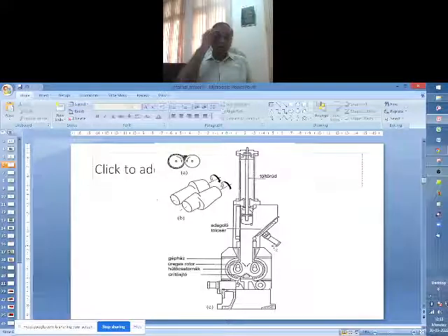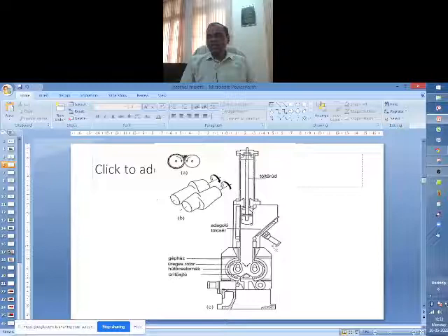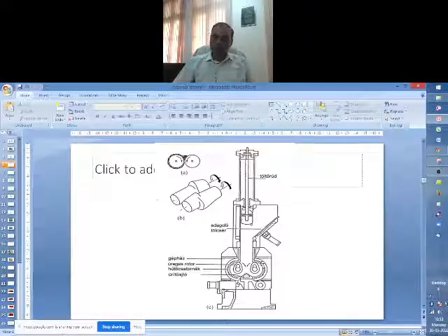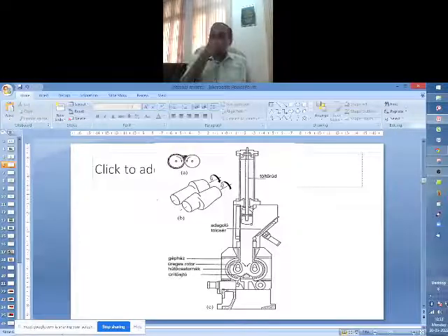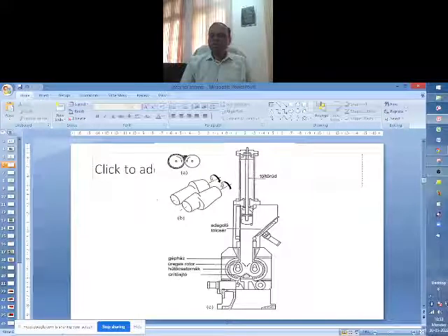But it is not always the time that controls. That is why I said, at what point is it dumped? One possibility is at a certain time after the ram down, say after 3.5 minutes or so many seconds, it will be dumped. Another possibility is at what temperature. You are continuously monitoring the temperature of the stock because there are thermocouples here. At what temperature you want to dump is also a protocol. You don't worry too much about the time. Once the temperature comes to 100 or 70 or 85, whatever it is, then irrespective of the time it has remained in the system, it will dump.